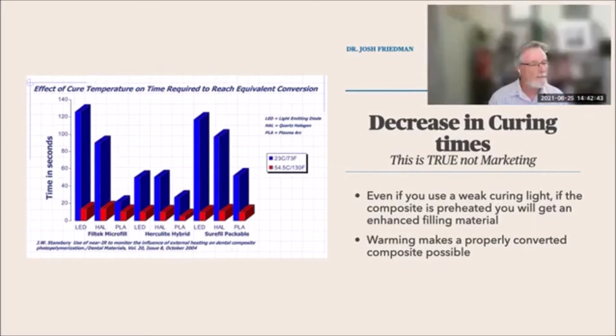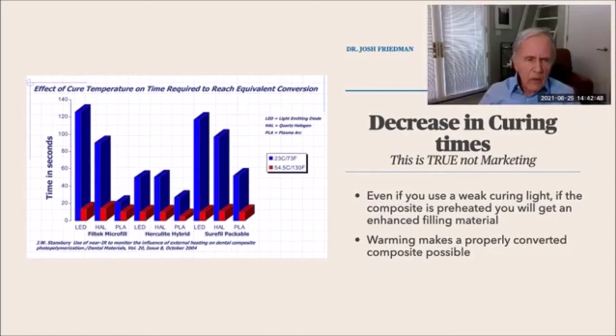23 degrees C, we see what we would normally expect, that with a weak light, it would take longer to cure. In this case, it's 120 seconds. And these cures are based on that FTIR technique that I talked about earlier. So it's cured to a probably greater degree than most clinical materials are cured. And the same thing with the halogen, and that took about 90 seconds. And of course, the plasma arc light, as you can see, had the shortest cure time, around 20 seconds. But that's the room temperature. And the other materials followed in a similar way.